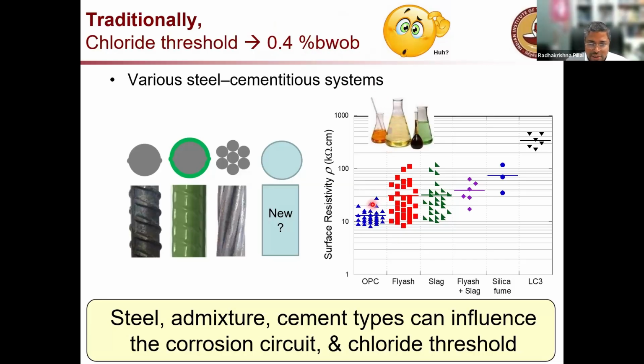Now, before going to the next slide, I want to also show you the advantage of using different chemical admixtures, different mineral admixtures or supplementary cementitious materials. Look at these blue markers here. This is OPC, ordinary Portland cement. The resistivity of concrete made with ordinary Portland cement is in the range of 10 to 20. You can see here very few blue markers around 20. This is a logarithmic scale here. Now, when you mix a little bit of fly ash or slag, etc., you can see that there are a lot more numbers in the higher range.